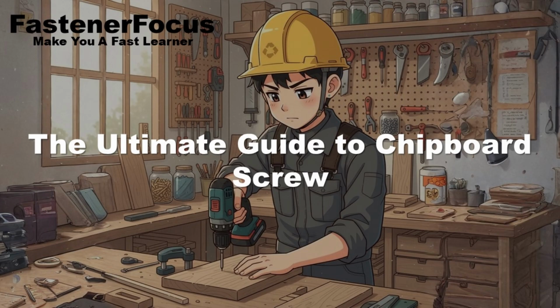Okay. But even more important is thread rolling. Instead of cutting the threads with something like a lathe, which would interrupt the grain structure of the steel. You're cutting into the grain. Right. Instead, the threads are formed by pressing the screw blank between two very hard dies. So you're displacing the metal, not removing it. Exactly. And this displacement forces the grain structure of the steel to follow the contour of the thread. This flow line significantly increases the fatigue resistance and the strength of the threads, making them much less likely to strip or shear when they're subjected to immense torque. It's an optimization for maximum fatigue resistance.